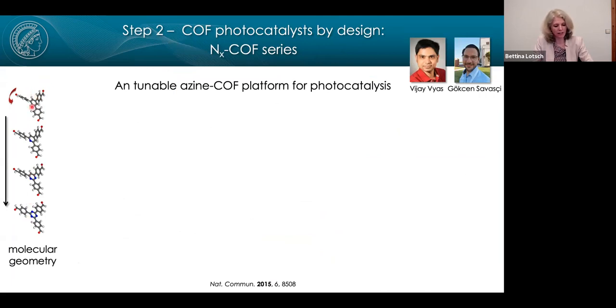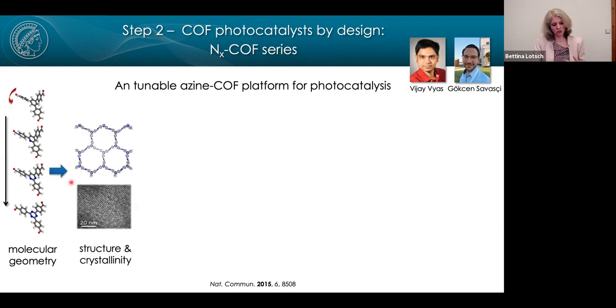So going from phenyl or triphenyl aryl without nitrogen in the central ring to the pyridine and pyrimidine and triazine system. And as we do that, we're flattening out this twisted building block. So here, this is a very twisted building block that also translates in the structure of the COF. And we're flattening this out towards this triazine system here. And we notice that that actually directly translates into the structure of the COF.